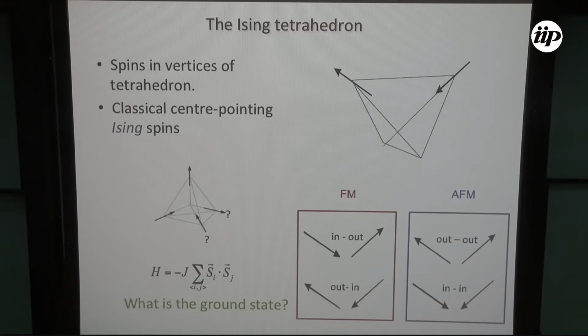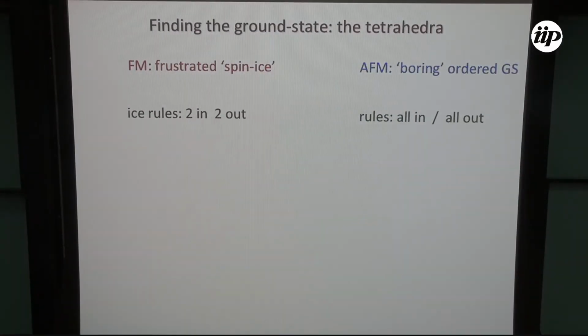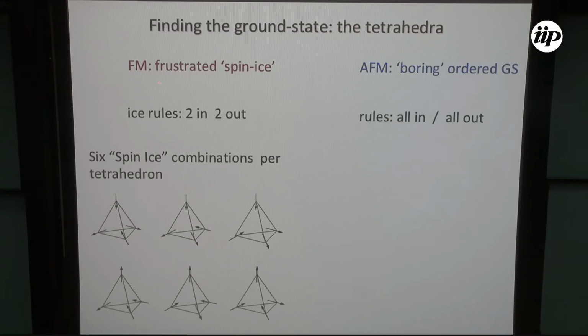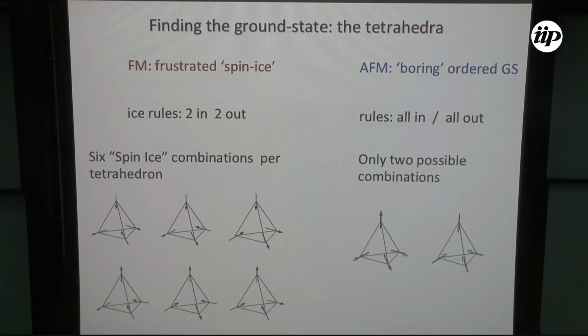So what this means is that the ferromagnetic case has this rule that tells you that of the four, two have to be pointing in and two have to be pointing out, while the antiferromagnetic will be this boring case, if you want, between inverted commas, because in the first part I'm going to talk mostly about the boring stuff, where all of them have to point out, and all of them have to point in. So in the frustrated case, where you cannot satisfy all the bonds, you have 6 possible combinations of 2 pointing in, 2 pointing out, while in the case of all out, all in, you have only 2 possible combinations. But this is for a single tetrahedron.